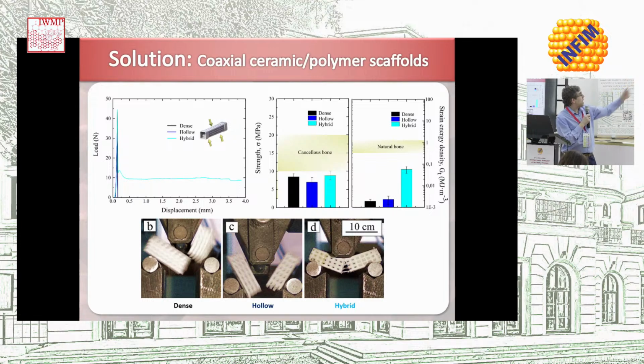Whereas when you have the polymer on the inside of the channel, even long after initial failure, you can still withstand the load. Okay, this material, the one on the right, has been tested for a very long displacement. So you've been stretching those fibers for a long time, and still your material is in one piece. Okay, the ceramic is broken, that's for sure, but the material still sustains some load. So that's what we wanted, and we get it.